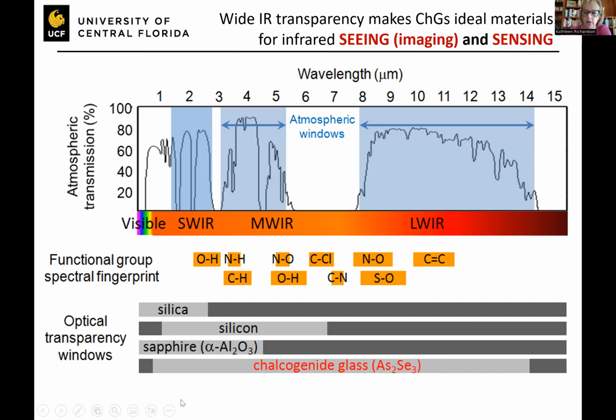So shown in the bottom panel is where many of the materials you might be familiar with transmit across these windows. So the light gray is where these materials are transparent. The black or dark gray is where they are opaque. And what you see is that one representative glass material, arsenic selenide, transmits very broadly over this full region. And so if we can think about making these materials, and this is just one composition based on arsenic and selenium, in a form factor that allows them to be integrated into structures that can be put into sensing applications, we can use it to detect a wide range of species.